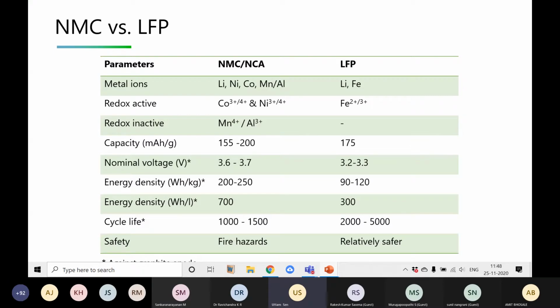Okay. In case of NMC, the material level capacity is around 155 to 200. Currently, it is 200 and 220 also, in present day NMC and NCA. Yeah, in case of LFP, it's mostly a single metal system. So this is lithium iron phosphate, where iron is the active redox couple, and it is having a theoretical capacity of around 175 milliampere hour per gram.